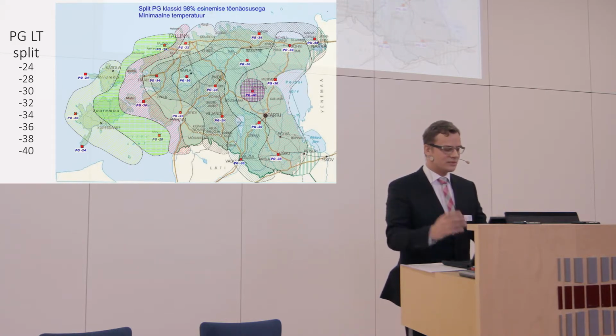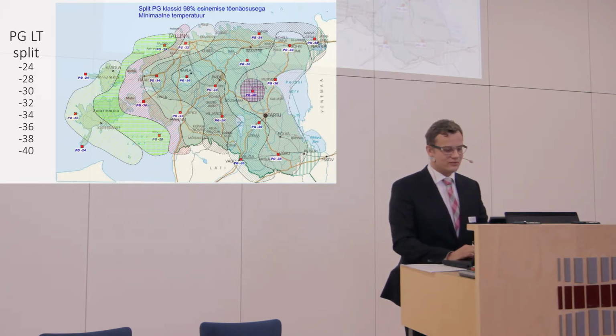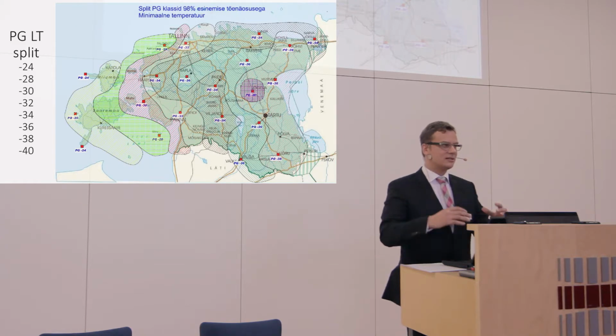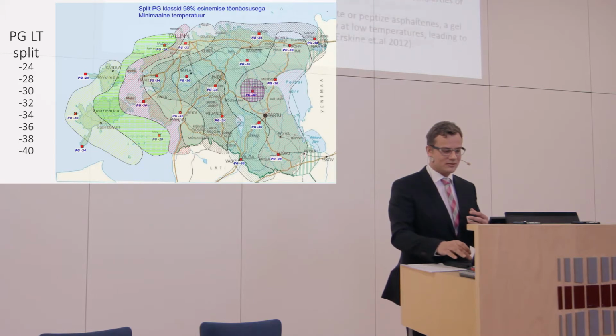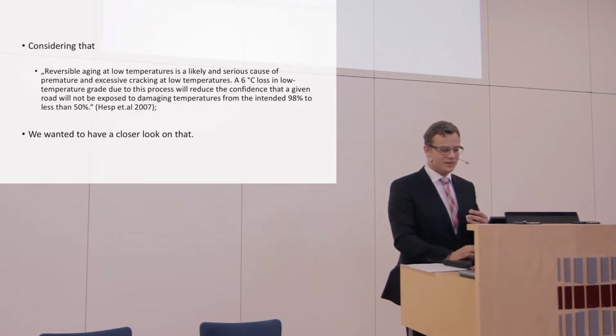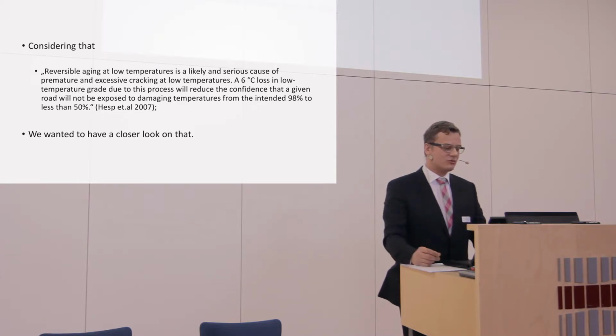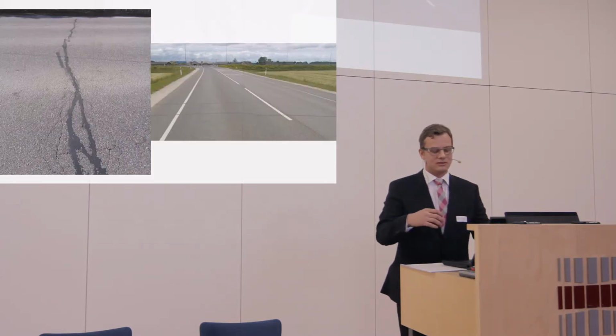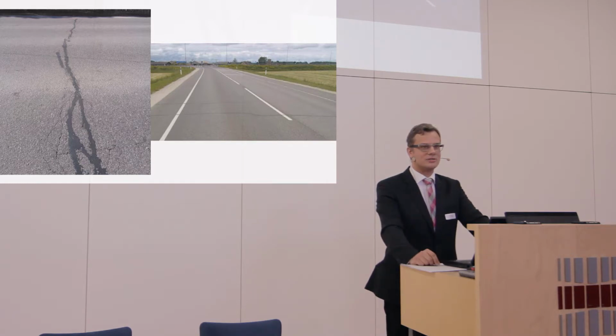So when we put a bitumen inside, which has the low temperature grade for minus 36 degrees, there will be no cracks inside it. But when we use a modification with oils, then we reduce this confidence from 98% to less than 50%. So there's a big grade loss, and in the results we can see this kind of damage on roads. Well, these are not very bad damage. There's a lot of worse cases.